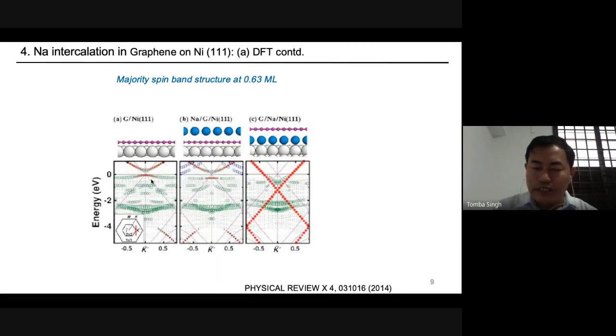Here we see the straight lines. These straight lines are the pristine graphene band structure, and they meet at the Fermi level. And these green balls are coming from the bands of the nickel, and the red ones are coming from the graphene. So we don't see a proper Dirac band, and there is even a band gap.